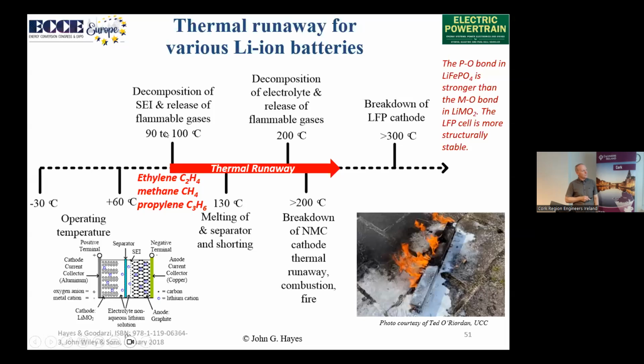Our pack is designed to operate, roughly, between minus 30 and plus 60. Now we'll show that it's not great at minus 30. But what happens at about 90 to 100 degrees, or maybe lower, is the solid electrolyte interface, that lithium barrier layer along the anode, is going to break down. It's going to break down and react with the electrolyte, and we're going to get ethylene gas released, methane released, and propylene. All of these are hydrocarbons, and Edison would have told you at Ford that those are great to burn. So that's happening very early on.